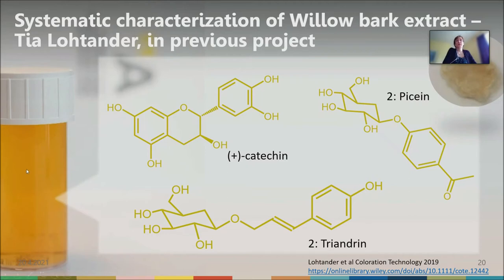So she combined the chemical characterization with also studying the absorption to cellulose substrates, and also showed that this willow bark extract could dye both the natural yarns and also films from nanocellulose, for example. But the willow bark extracts are not only interesting as a biocolorant.